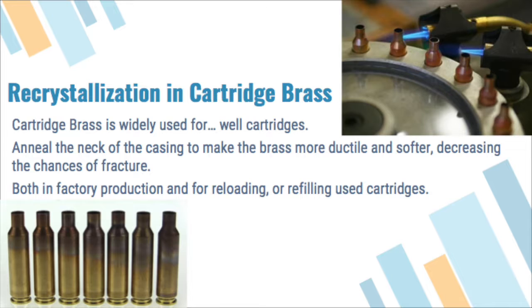Additionally, once a cartridge is fired, the casing can be reused. This is called reloading. By once again annealing the neck of the casing, it becomes easier to set a new bullet inside of the casing, and reduces work hardening in the casing from being fired, which extends the lifespan of the brass casing by preventing fractures from gunpowder combustion. Eventually, the casings will still fail, as annealing can only repair the microstructure of the brass, not the macrostructure, and small deformations can grow massively between firings.